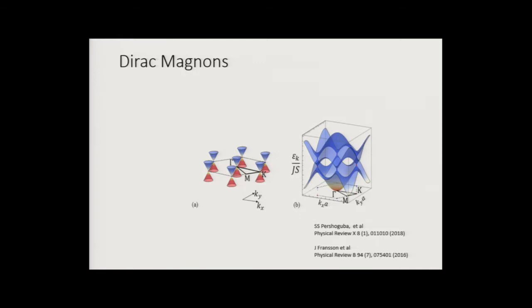So then another example of what we were looking at, I'm not showing the Josephson junction array, but you can think about putting niobium grains, or some superconducting grains, into the honeycomb lattice or any non-Bravais lattice. If you think about the tightly bound pairs, which are essentially, at low temperatures, Cooper pairs, effectively bosons living on this network, one can see immediately that you will have in the honeycomb lattice the Dirac crossing point for the dispersion of the collective modes of the Josephson junction array. All right, so the example I want to emphasize here is the case of the honeycomb ferromagnets.